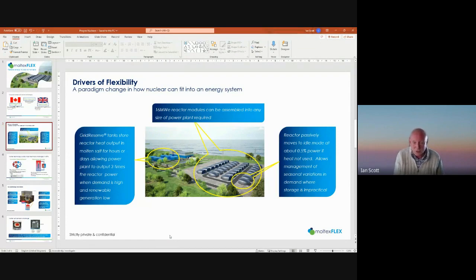The other two flexibility factors, which are important, is first, because this reactor operates at high temperature, it can use thermal energy storage, which again is not new. It's been used in the solar power industry for many years. It is an extremely cost-effective way of storing energy. Storing electricity is expensive, very expensive. Storing heat is actually really very cheap. So by using thermal energy storage, it allows us to have a reactor which can operate 24 hours, 7 days a week, but output its energy for perhaps only 8 hours a day, but at three times the reactor power. Economically, that's of enormous importance.